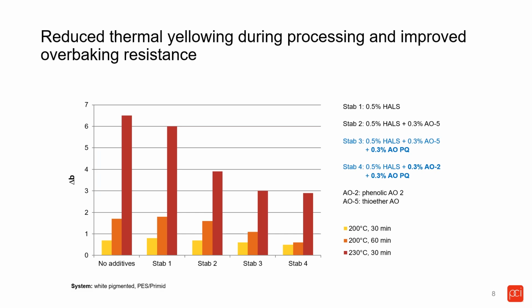So the temperature that we see here is the temperature of the oven where the curing is taking place. Usually when we do overbaking, which is a very common practice in the powder coating industry, either you extend the curing time from 30 minutes to 60 minutes, or you increase the temperature of the oven, which is in this case 230 C, but you keep your curing time the same, which is here 30 minutes.